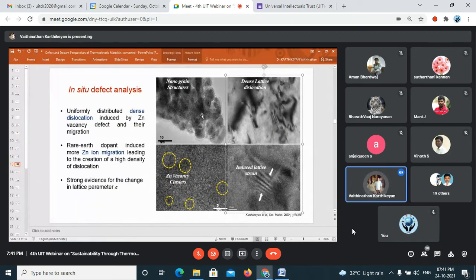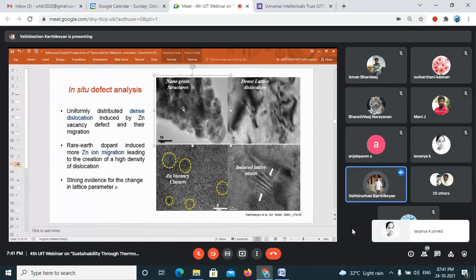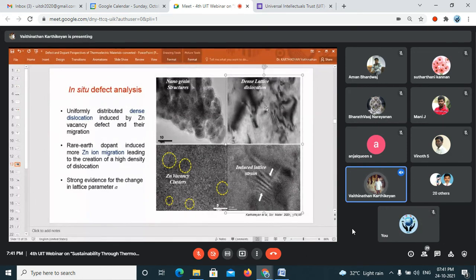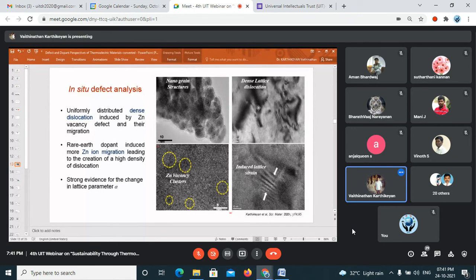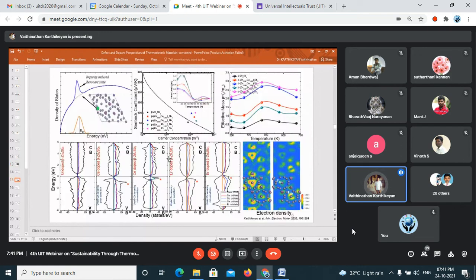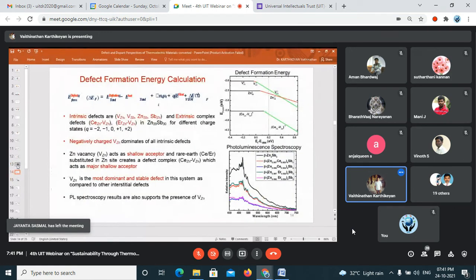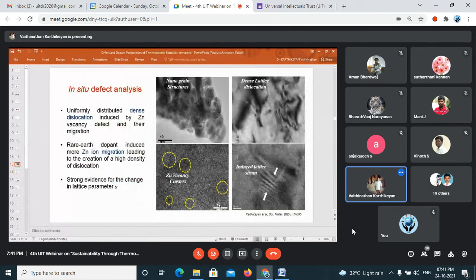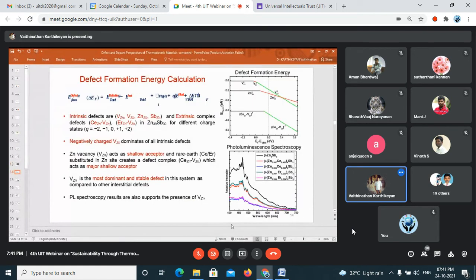This is the 10 nanometer tip I mentioned. You can see these are nano grain structures where circular, oval shapes or individual nanograins in the material are detected. And this TEM image demonstrates the dislocation in the lattice and the zinc vacancies are circled. Yeah, I think this is for the defect understanding.